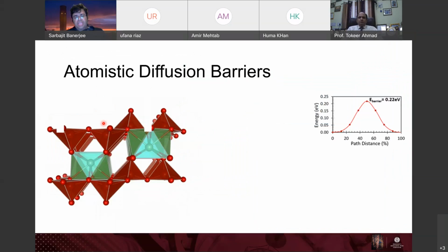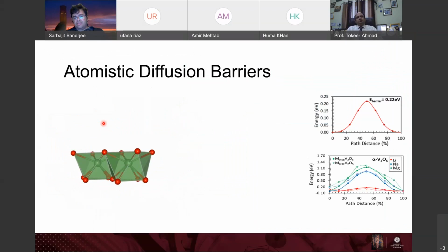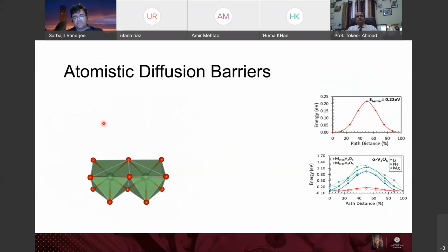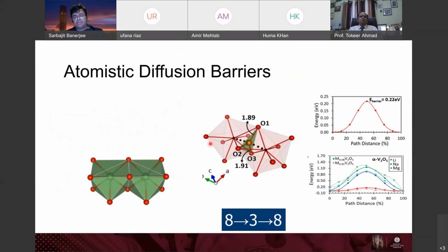So about a decade ago, we started thinking about whether we can dive down into the chemistry of the system. And so if you actually look at the lithium ions and where they sit inside the lattice, it turns out there is a pretty large change in the local coordination environment as the ion moves through the lattice. So you go from being 8 coordinated to being 3 coordinated in the transition state to being 8 coordinated again. So what this means is that there's a lot of bonds being broken, new bonds being made, and then bonds being broken again, but a big change in coordination as the ion moves through, and therefore the barrier tends to be pretty high, about 0.22 electron volts for lithium, not that high, but relatively high. And then, as you can see for other ions, this becomes a huge challenge.